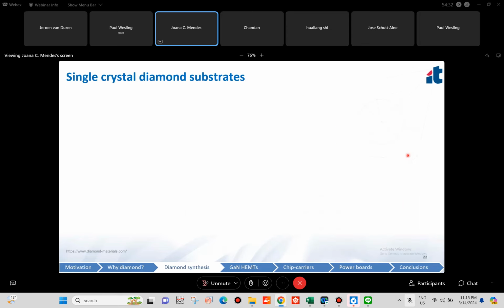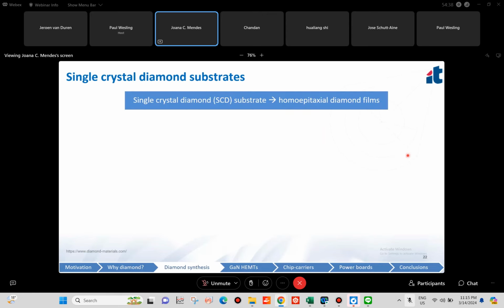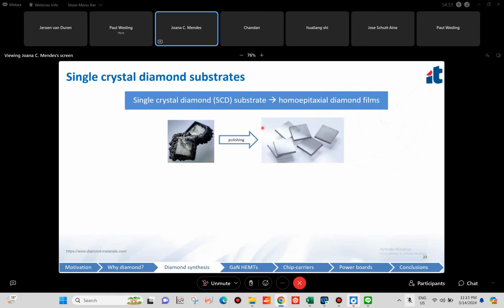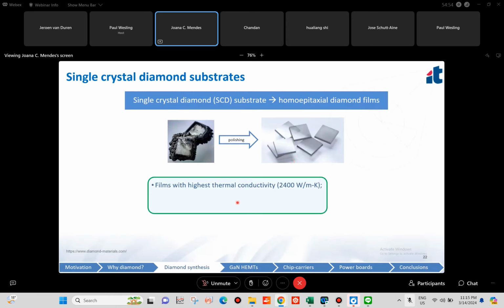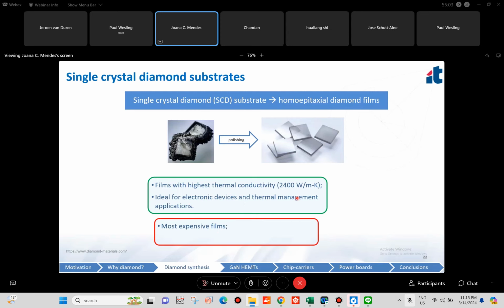And one more thing that I'd like to say is that we can either use a single crystal diamond substrate, and then we have homoepitaxial diamond films. So typically we use an HPHT crystal, and this is what we get out of the CVD deposition. After polishing, we get these nice transparent diamond substrates, which have the highest thermal conductivity of 2400 watt per meter Kelvin. And these are really ideal for electronic devices and thermal management. However, they are very expensive, and the limit is to a low area, up to 10 times 10 millimeters square. And then after my talk, Jeroen will tell you that no, we can actually grow them much larger, but I will let him explain that.